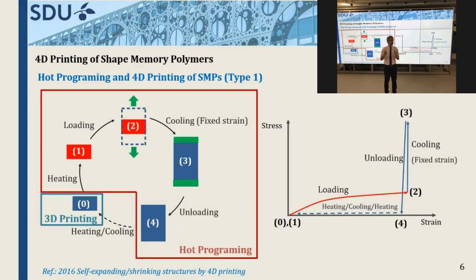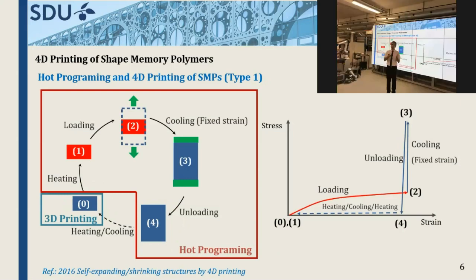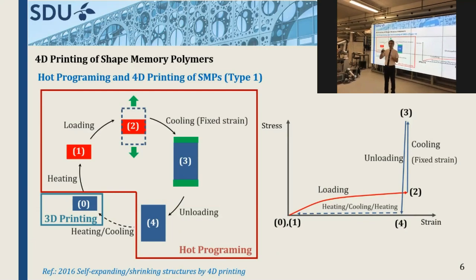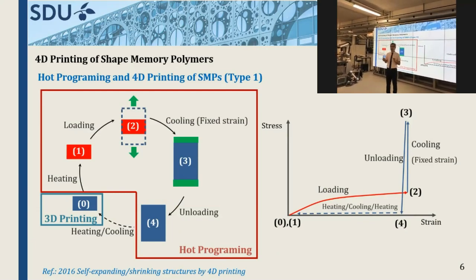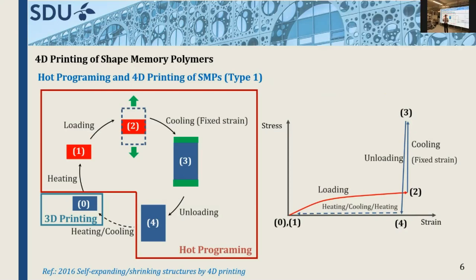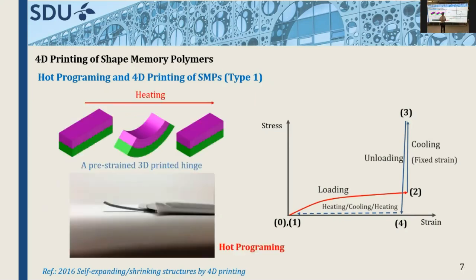If we add this feature to additive manufacturing, as you can see, at the first stage we can fabricate the material or structure using 3D printing. The programming can be done in another stage. We can raise the temperature, add some loading, and change the shape. At the fixed configuration, we can unload. What we gain is a temporary configuration. This temporary configuration can be actuated by the heating and cooling process. Let's see what's happening.